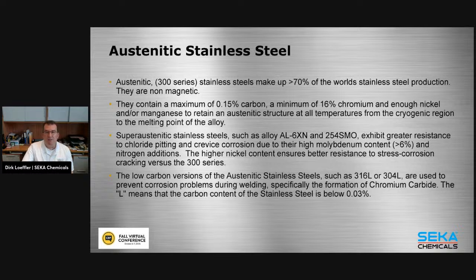So for our purposes today, we're focusing on austenitic stainless steel, 300 series. Generally in the brewery we find 304, 308, 316. Some of the characteristics: a maximum of 0.15% carbon, a minimum of 16% chromium, and enough nickel and manganese to retain the austenitic structure. That is the internal metal structure that also makes it non-magnetic.